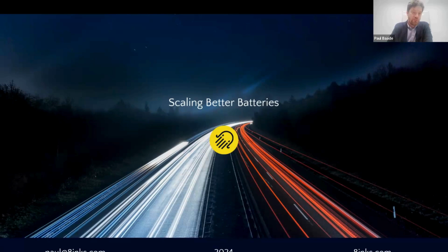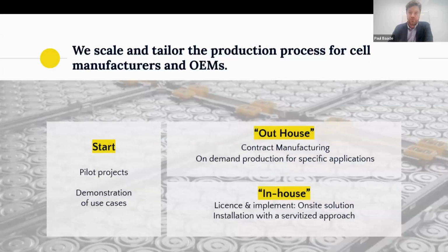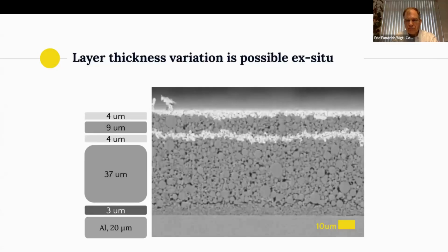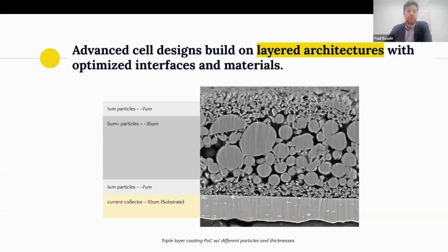And the die manufacturer that we work with, I wanted to give one example from the packaging industry, where the target was 20 micron film for barrier films. And they are within 0.5 micron of that accuracy. And the films that I showed you, actually, these are uncalendared film. So these cross sections and uniformities, they come straight out of the coating. For any kind of product, it needs to be optimized. But I think for the development speed that we do, it's acceptable, and that's also the feedback from our pilot partners as of today.